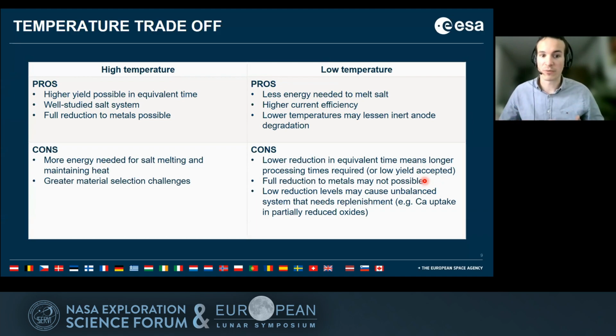At lower temperature, we see that we still have quite a good reduction if you're interested in the oxygen, but so far you don't get the metal. However, you have to keep in mind that these are all 24-hour experiments. So the 40% reduction we got at 660 degrees, for instance, might not be the maximal reduction. By making it 48 hours, we might get a much higher reduction. We'll have to try this later to see if there is a ceiling at this reduction, or if we can also get a full reduction below 700 degrees. That would be the next step. But so far we see that we have higher current efficiency. That's also quite an advantage.